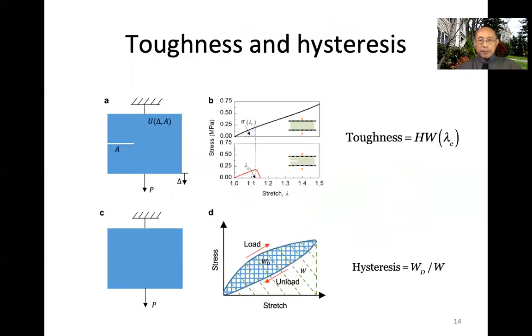We tested it by experiment. So here's the experiment we do. We make a composite, we make a cut, and do cyclic loading to measure the threshold. And then we also measure dissipation, the hysteresis, without any pre-cut. We measure the stress-strain curve, loading and unloading. If a material is very elastic, the loading and unloading curves will be very close, so this area WD will be very small. We measure this amount of hysteresis by a dimensionless ratio, WD over W, meaning this hysteresis area over the entire area underneath the stretch curve.